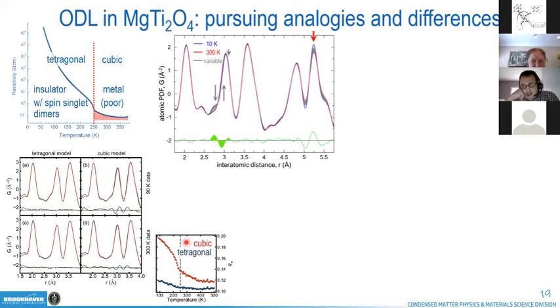So let's just take a look at the stack of data and see what happens as you cross the transition. What you see here is a stack of PDF data doing exactly that. There is a signal associated with the dimer distance in this titanium spinel that disappears. It goes from blue, where there is some kind of distortion, to red, where presumably the distortion is removed in a pretty much continuous way, and that intensity is placed at a slightly higher location. However, this peak does not show standard thermal behavior. Standard thermal behavior would be that as you heat up the system, the peaks become broader, which is not what this peak shows. It's a dominant effect on that peak.